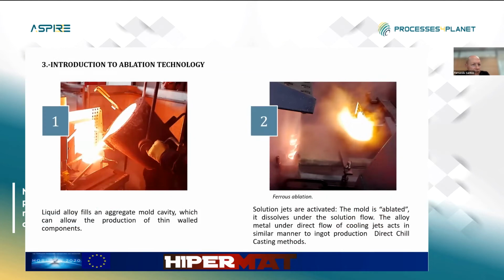Finally, those are tests that we carry out in AZTERLAN, and you can see here a high melting point alloy being cast in picture 1. Then it's tilted, and when it's rotated, you can see in picture 2 how water spray has dissolved the mold, and we are impacting the solidification, the solidifying part.